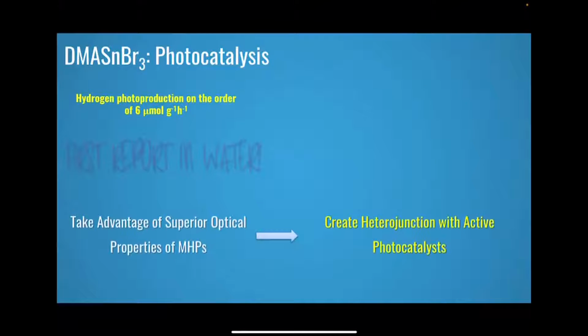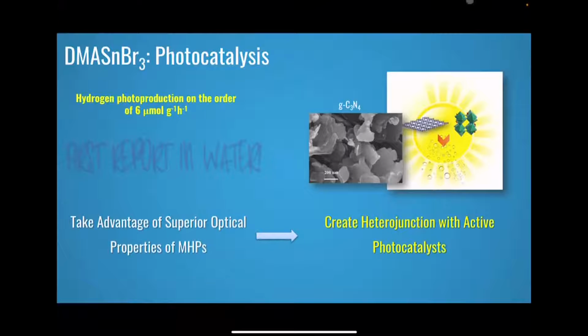Of course, then we thought to take advantage of these superior optical properties of metal perovskites and this impressive stability of these perovskites, and we thought to create heterojunctions with other active photocatalysts, and in particular we selected graphitic carbon nitride. We run a lot of work on this material. So we create composites, heterostructures, by combining graphitic carbon nitride, which is a visible light photocatalyst, a yellow material with a band gap around 2.7 eV.